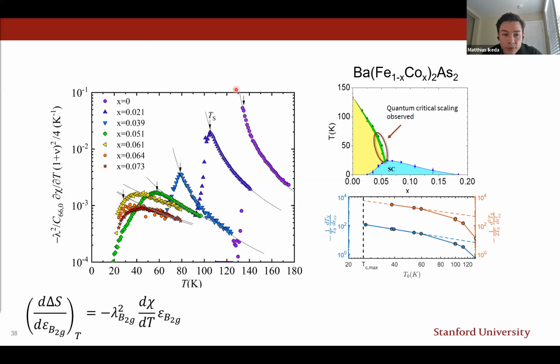And basically the fits that we apply here, corresponding to this formula, originate purely from a derivation from a Landau free energy expansion that only considers nematic degrees of freedom. So we do not consider any other degrees of freedom. We fully neglect the lattice and other degrees of freedom and still arrive at this form of the elastocaloric effect, which describes the data almost perfectly, right?